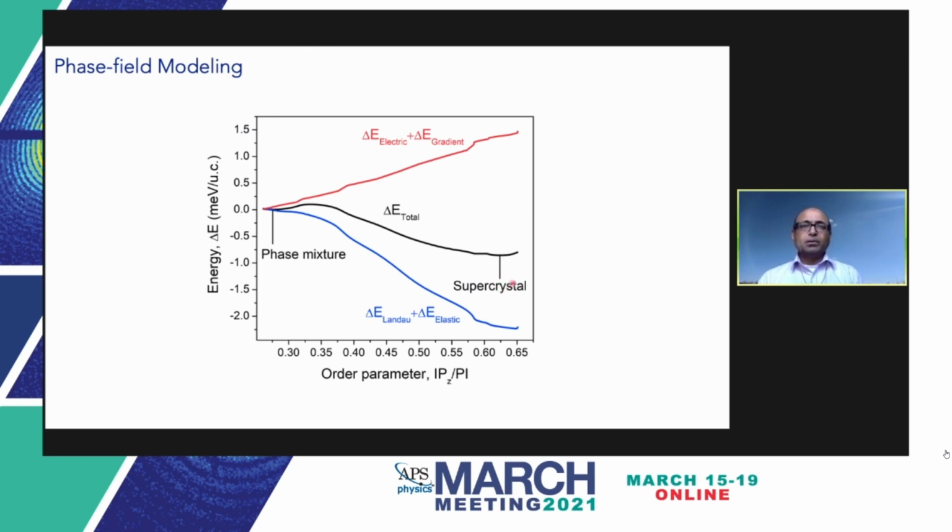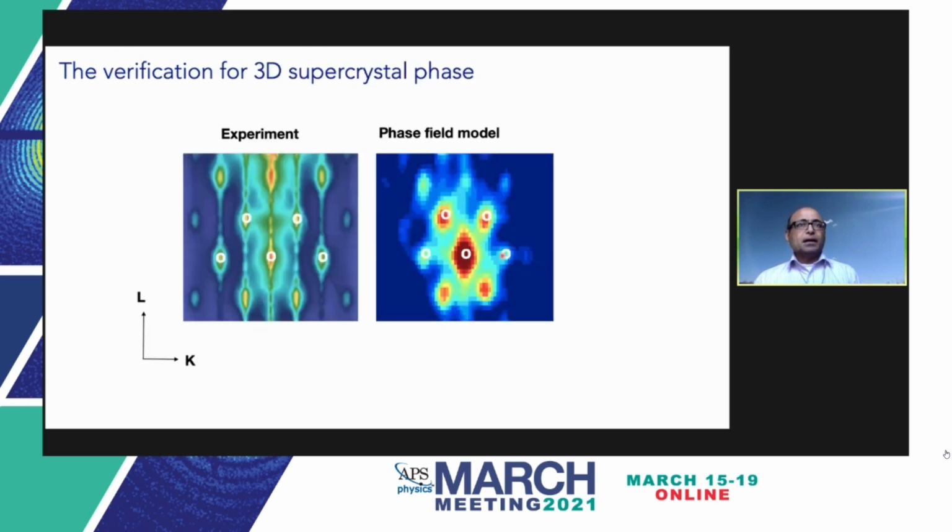This is a supercrystal state. And the interesting thing is this is metastable. It sticks around for a long time, as long as you want, until you heat it to 450 Kelvin. But if not, it'll stay here. But it is not an equilibrium state. If you erase it, you can get it back only through non-equilibrium means by hitting it with an ultrashort pulse of light. You cannot just do equilibrium things and get this phase.